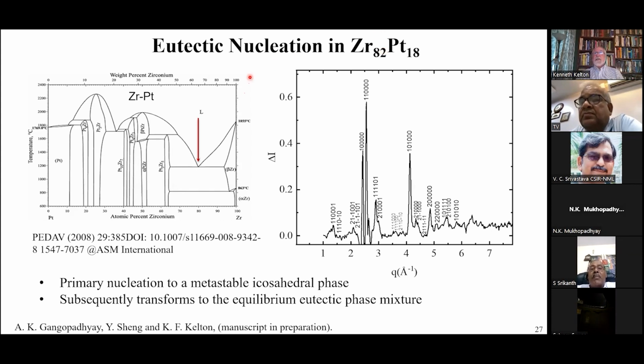And here's some experimental evidence, at least in this one system, where the first phase to form was a metastable quasicrystal. Again, we know that this particular liquid has a lot of icosahedral order. We've measured that from the liquid. Also, it has been known for at least 15 years that if you quench this very rapidly, you will form an icosahedral quasicrystal. It's not a very good one. It's a nano-size icosahedral quasicrystal. But it's all consistent, and it seems that in this case, eutectic nucleation proceeds first by the nucleation of a metastable phase, which then transforms to the equilibrium eutectic phase mixture.